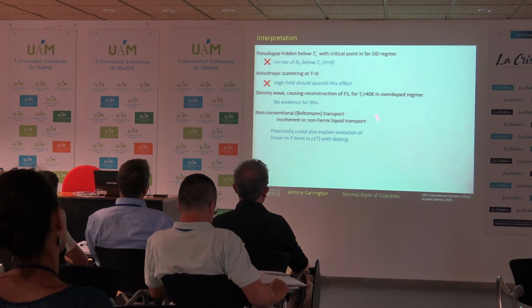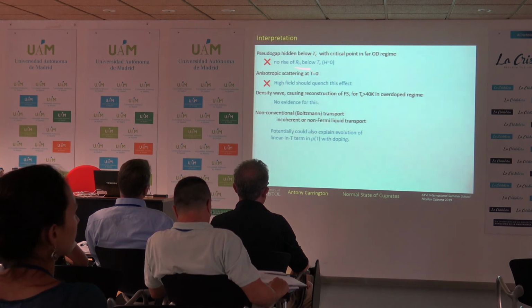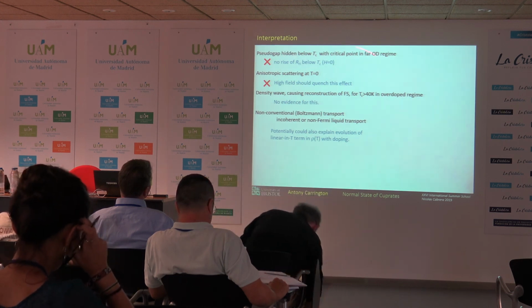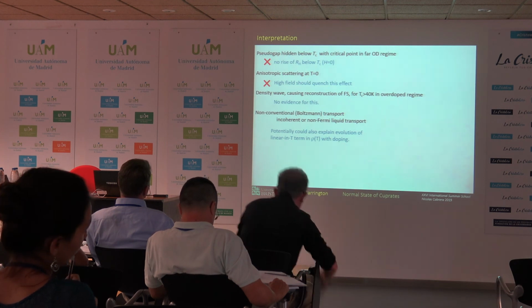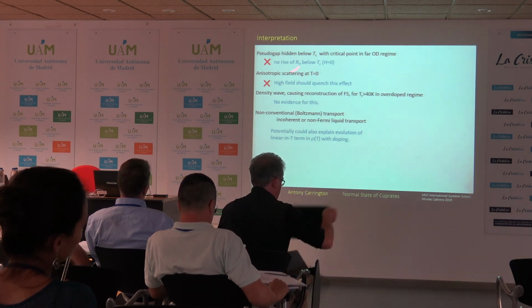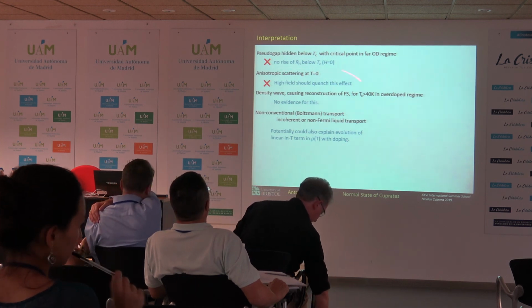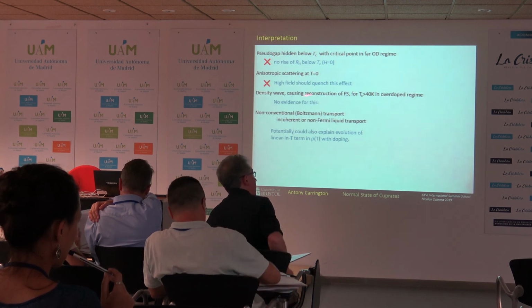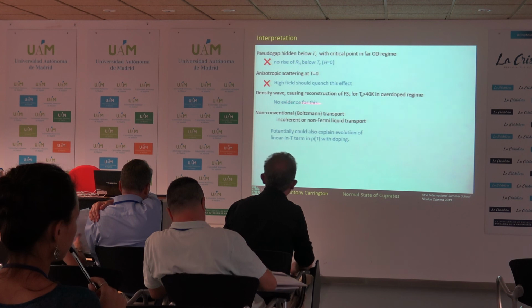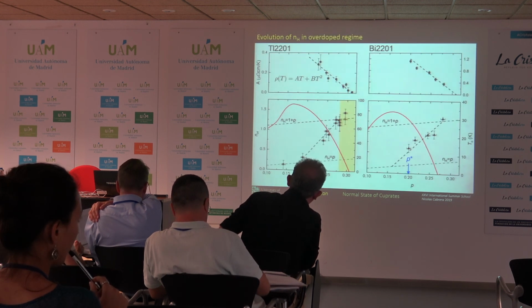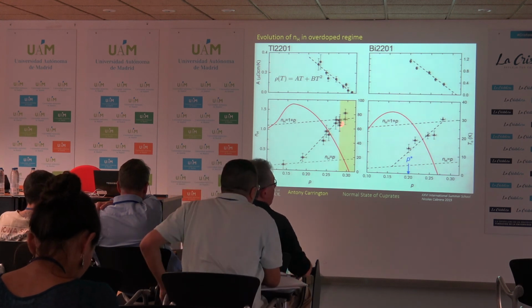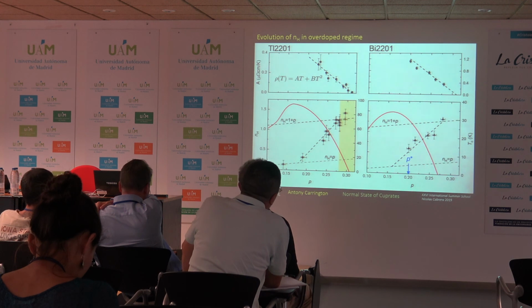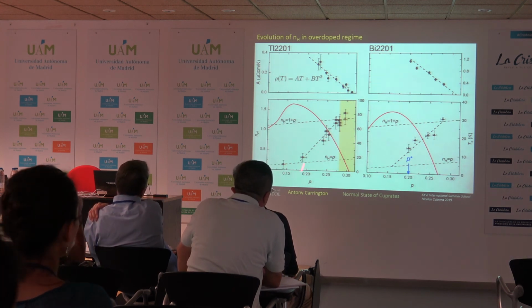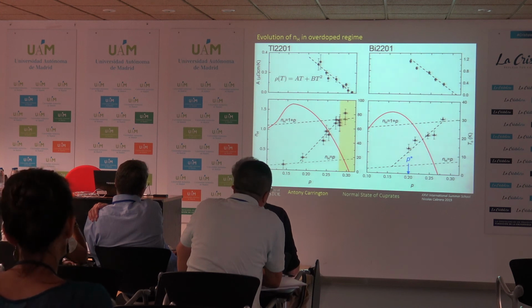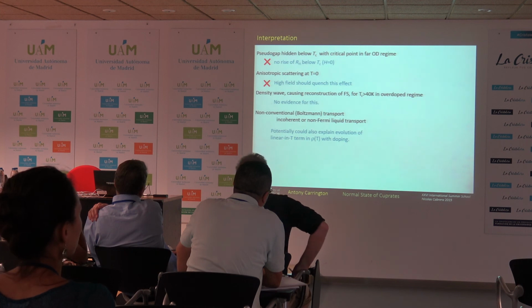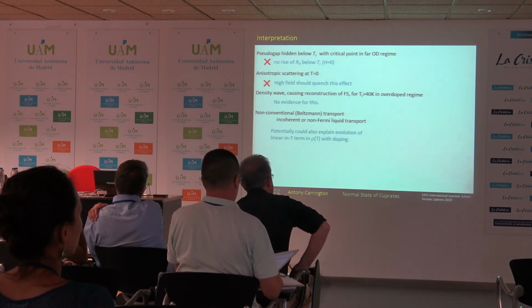Okay, so what does this all mean? Well, it means that this rise of the Hall number isn't linked to the pseudogap because we don't have a pseudogap. It's probably not linked to anisotropic scattering because 60, 70 Tesla should quench this effect. Density wave possibly could explain it, but again, there's absolutely no evidence for this. What we're really left with is that this is a mark of the non-Fermi liquid, non-Boltzmann nature of the charge transport in the cuprates, which seems to extend almost all the way to the edge of the superconducting dome. And I think at that point I'm going to stop. Thank you.